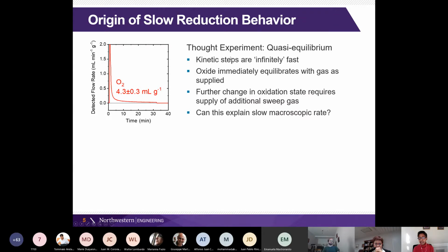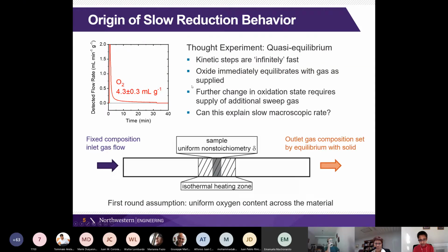So let's do a thought experiment. Let's imagine that the material is in quasi-equilibrium, meaning the kinetic steps are infinitely fast. So there is no delay due to surface reaction. There's no delay due to diffusion. That means that the oxide would immediately equilibrate with the gas as soon as it's supplied. And any further changes in oxidation would require an additional supply of the sweep gas. So we want to see, can this explain the slow rate of oxygen evolution?